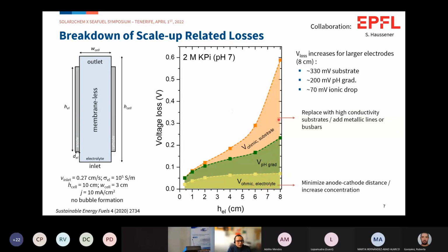In the case of substrate ohmic loss, we can minimize this by replacing the FTO substrate with high conductivity substrates, like the ones Adelio mentioned towards the end of his talk, or by adding metallic lines or bus bars like it's done in the photovoltaics community. In terms of electrolyte ohmic loss, we can minimize the ionic transport pathway or increase the conductivity by concentration. What about the pH gradient?